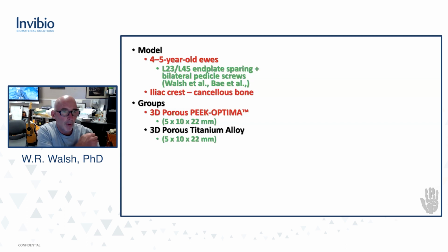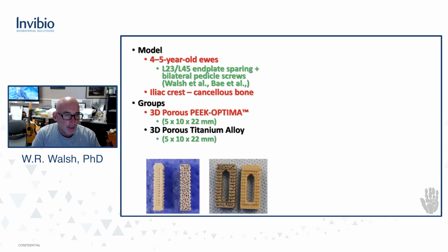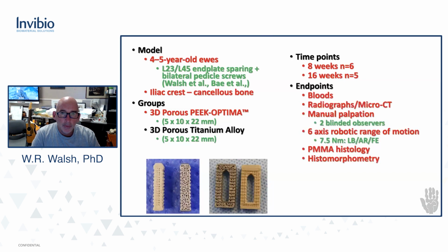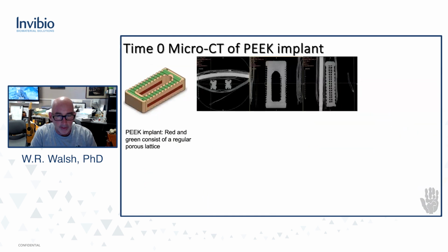We had 2 groups, porous PEEK Optima and porous titanium alloy, and those are the images of the implants. We did 2 time points, 8 and 16 weeks, and we did endpoints of blood work, radiographs, micro CT to look at imaging and the positives and negatives, manual palpation, range of motion testing, and importantly, histology. But it's when you compare these endpoints and you compare against groups where you can see some interesting things happen.